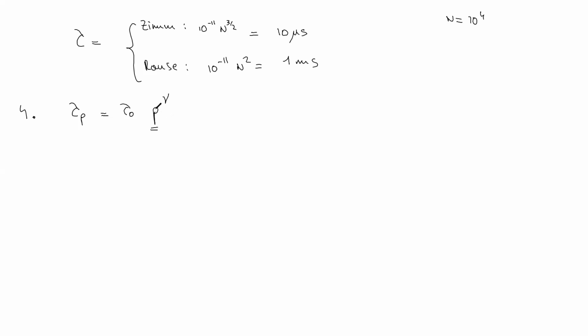If you have a change of conformation that involves the whole chain, for instance, I pull on the chain first and then I let it relax in the solvent, it will take a bit of time for that chain to go back to the coiled state, and then you will have capital N here. And for all the intermediate situations, you can have the formula here. So you have a hierarchy of timescales that was proposed by Rouse.